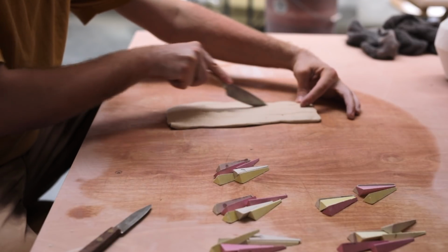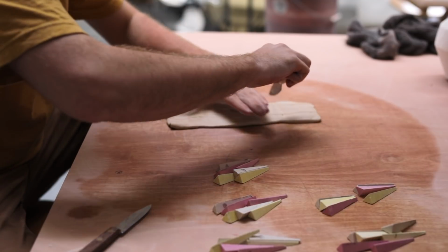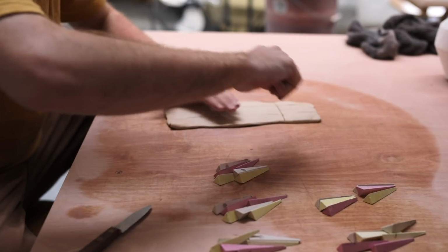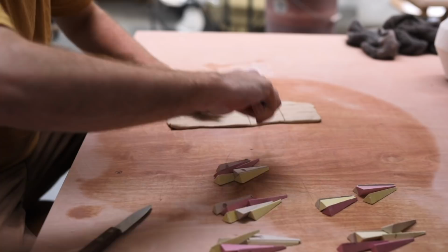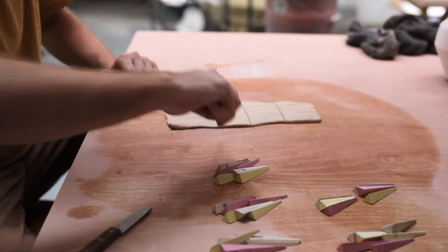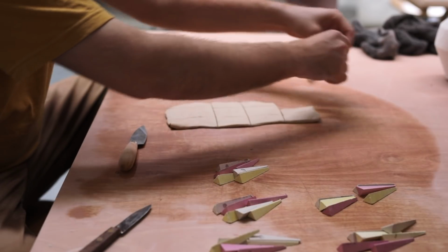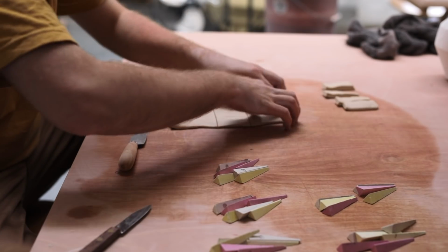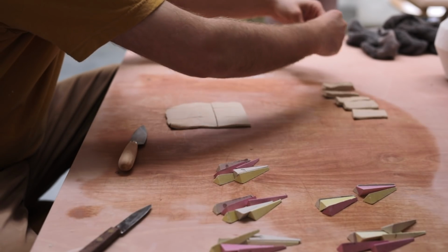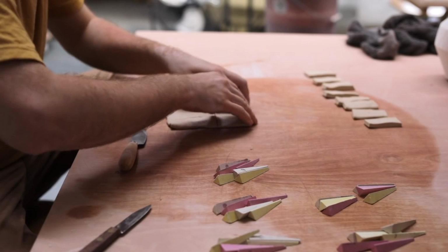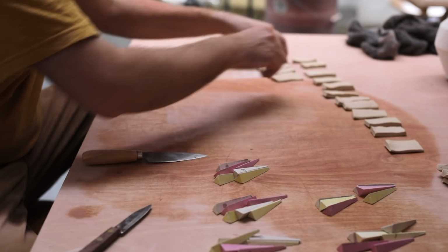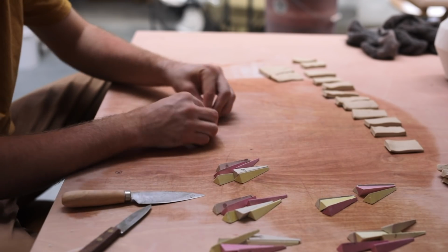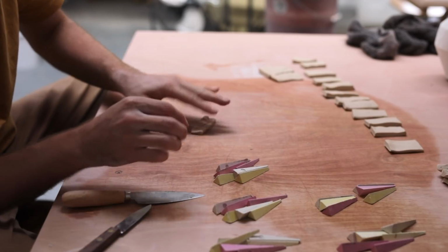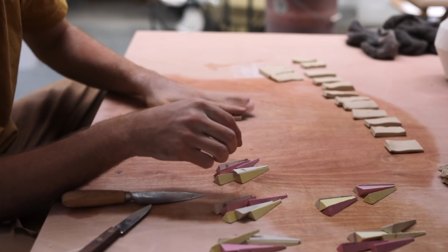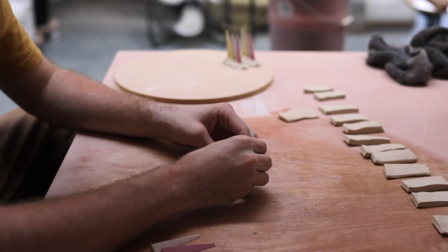This wadding material dries out very quickly, and I fire it in the kiln without bisque firing it first, which is another reason why I preemptively make all of these, as I don't want to place them into the kiln and fire them when they're still wet, as doing so can cause the wadding to explode if the temperature rise is too quick, scattering hundreds of little pieces all around the kiln, into pots, into the burners. It's a nightmare, so I make all of my cone packs a couple of days before I do any firing.